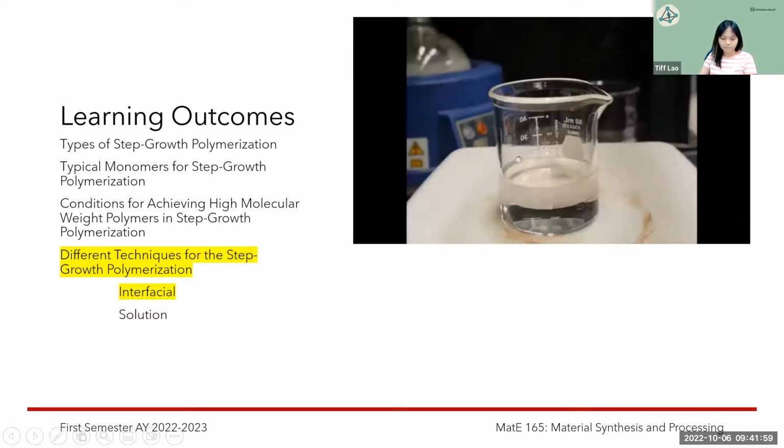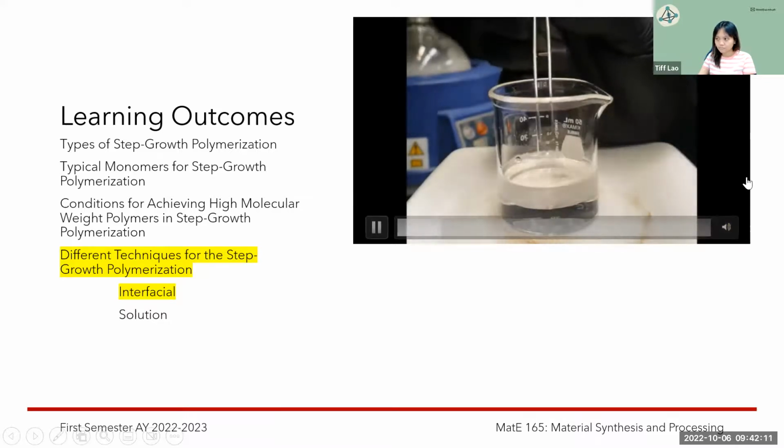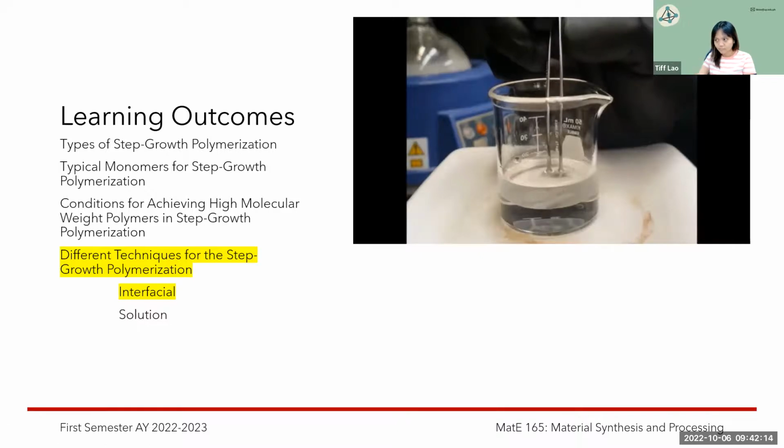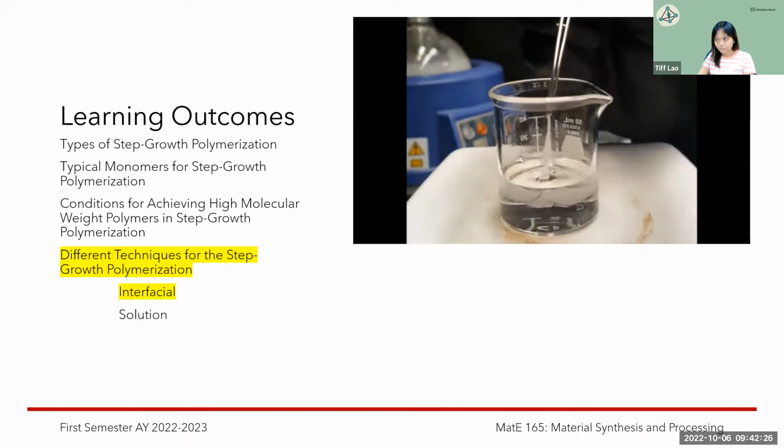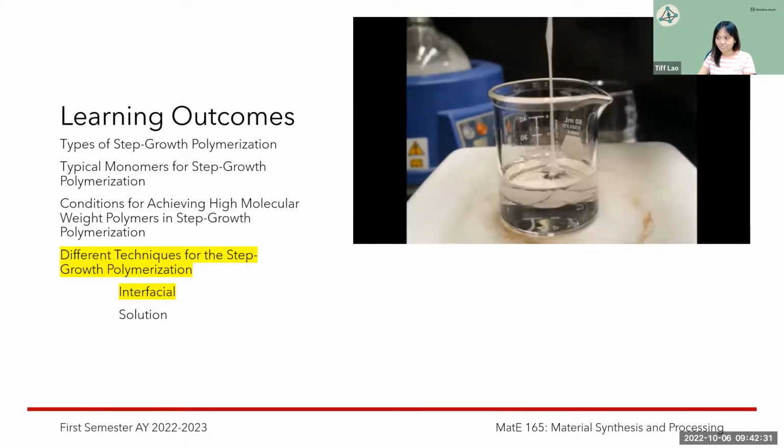Interfacial polymerization is a unique type of step growth polymerization in which polymer is formed at the interface of two immiscible phases. In this example, hexamethylene diamine is dissolved in water and makes up the bottom layer. The top layer is composed of sebacoyl chloride dissolved in hexanes. At the interface of the two phases, monomers react, forming the polymer nylon 610. By carefully removing the nylon from the interface, polymer will continuously form until either monomer is depleted.